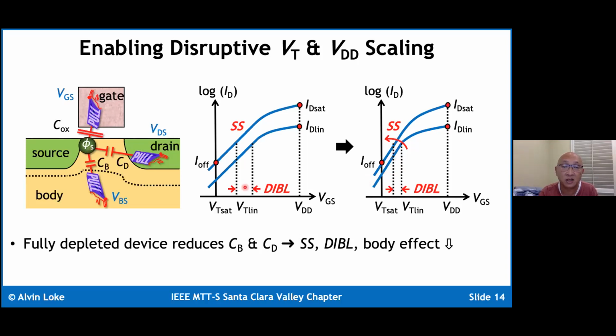The DIBL, which is a measure of the separation between the saturation and linear threshold voltages, is tighter. The body effect essentially is now going away, because with the body coupling being very weak, applying a body voltage will have very minimal impact on the surface potential, and therefore the body effect essentially disappears or near disappears in a FinFET node or a fully depleted device.